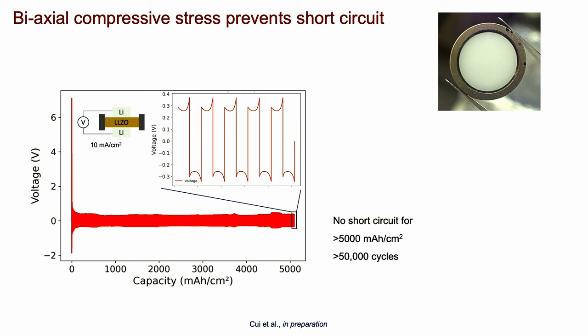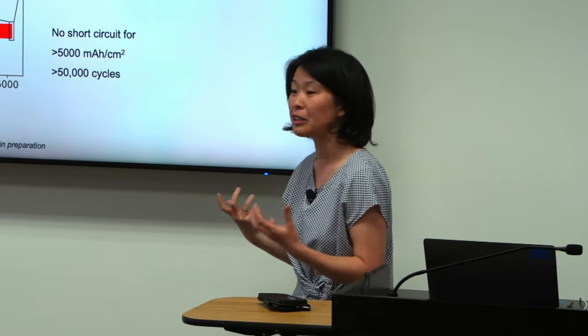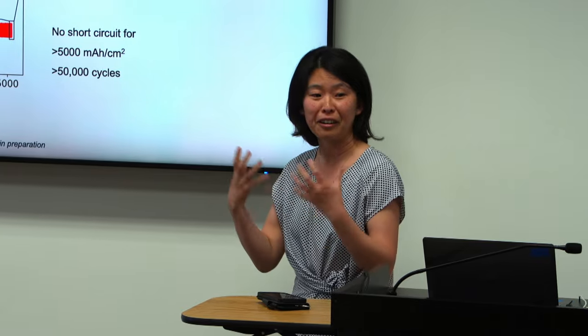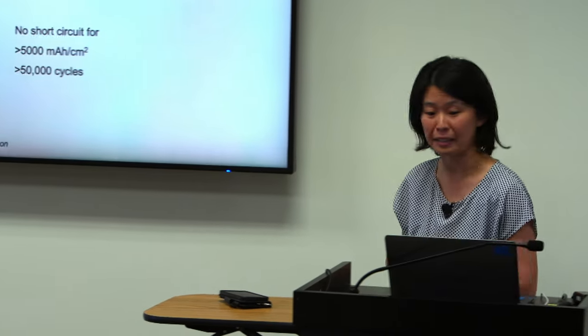In the end, we are able to have greater than 5 amp hour per centimeter squared of cumulative capacity. And if we turn it into cycles, it's more than 50,000 cycles. So this is 20 days of cycling. It actually hasn't broken at this point, but the researchers stopped the test, and we're continuing to test to push this limit even more. So this certainly seems like a demonstration that our central idea does work in this case.